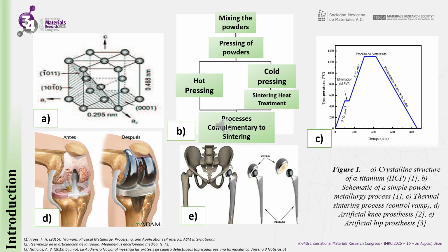H. Attar and collaborators compared the mechanical properties of commercially pure titanium parts and metal matrix composite systems composed of titanium and titanium boride, produced via selective laser melting, casting, and powder metallurgy. Three samples were sintered using powder metallurgy, with the compaction pressures varying only as a consequence of the process. The low concentration of reinforcing phases appeared to favor the formation of titanium boride whiskers in the titanium matrix. The objective of this study is to ascertain the impact of incorporating titanium diboride into the commercially pure titanium matrix during the sintering process with regard to its structural, microstructural, and elastoplastic characteristics.